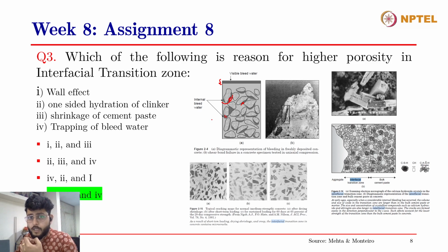So this internal bleed water accumulates across the boundaries of the aggregates, and after the concrete is hardened, this bleed water would either dry out, or it will get consumed by the concrete for the hydration process. Now, after the concrete is hardened, it cannot rearrange itself to a lower volume, and therefore when the bleed water goes away from these areas, that leaves a void. So that results in larger voids, and that causes an increase in the porosity of the ITZ. So trapping of bleed water is one.